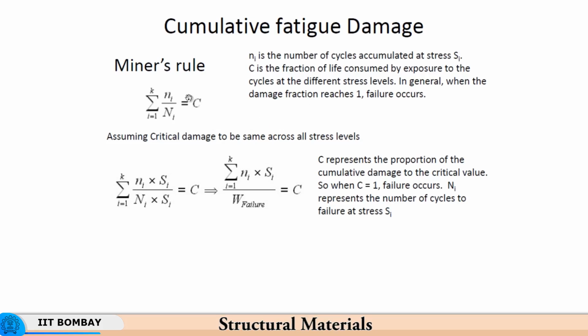So, now you will have n2 upon capital N2 getting added to this, because fatigue life is cumulative. So, small n1 upon capital N1 plus small n2 upon capital N2, and this way you keep on adding to the cumulative fatigue damage that would be introduced into the material as we subject it to different conditions in service. When the addition becomes equal to 1, then you can be sure that there is no further life present in the material.